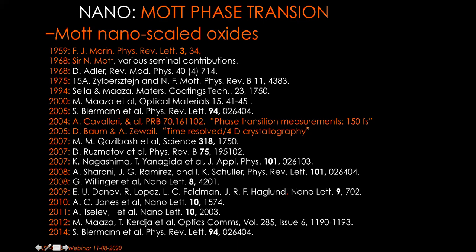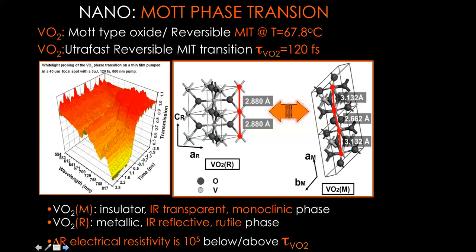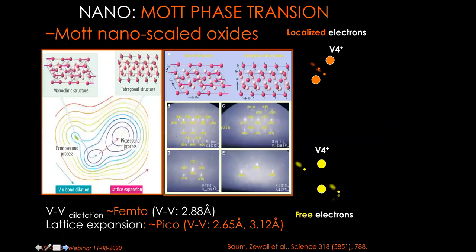And it was the first time where phase transition was measured, by Cavalleri et al. in the USA. I do not remember exactly where, but it is not of importance for us here. The point is that the phase transition from a metal to semiconductor, or from an insulator to a metal, is extremely fast, of the order of 120 femtoseconds. And the first one who observed this phase transition in the femtosecond regime via crystallography was the Nobel laureate from Egypt, Ahmed Zewail, and his student David Baum from Caltech.